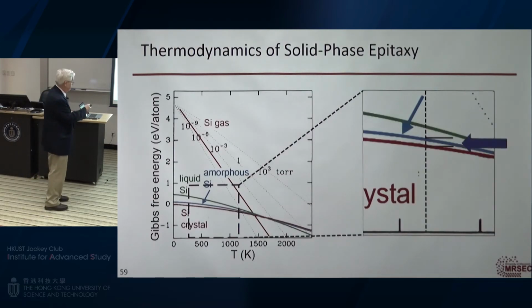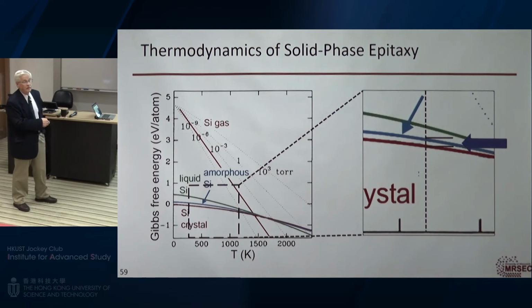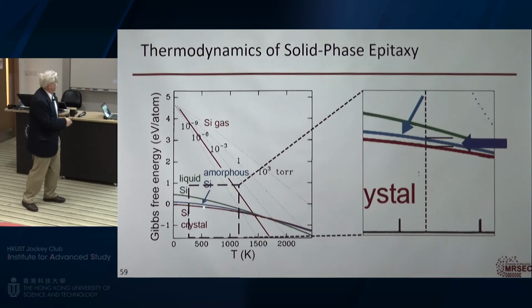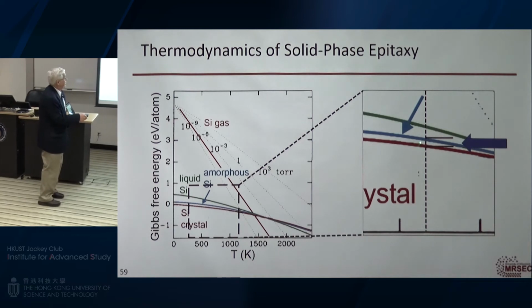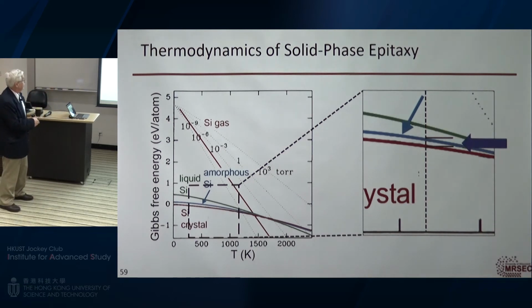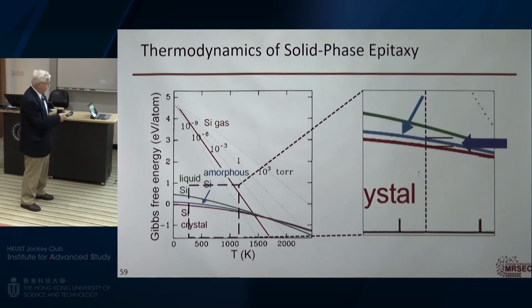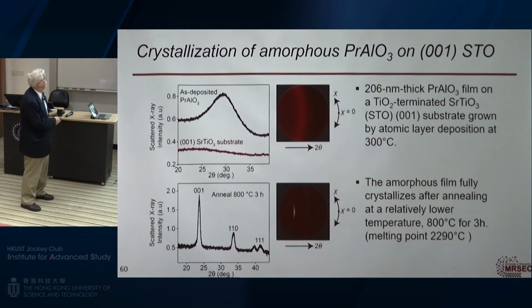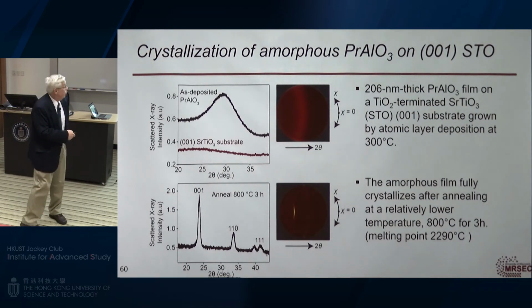So going back to this particular diagram, we started out by looking at the transition from liquid to crystalline at equilibrium. But the amorphous material actually has a slightly higher free energy than the single crystal. And we use that difference in energy to drive the epitaxial growth. And we're going to use two key concepts. One is that it's going to be easier to reorient atoms onto an existing seed to get epitaxial growth than it is to nucleate a whole new crystal. And so this actually works quite well.